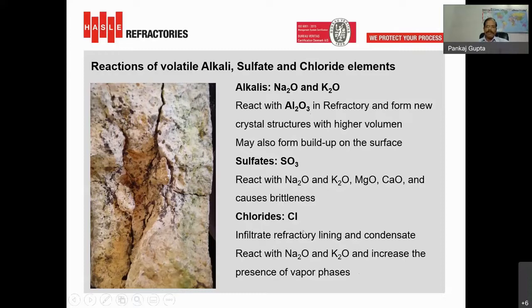Chlorides are very volatile and they infiltrate the refractory lining and condense, and when the temperature rises again, they come out again. Because of their chemical, corrosive nature, they make the refractory body weak. And also many times these chlorides attack the anchor system and make it fail.